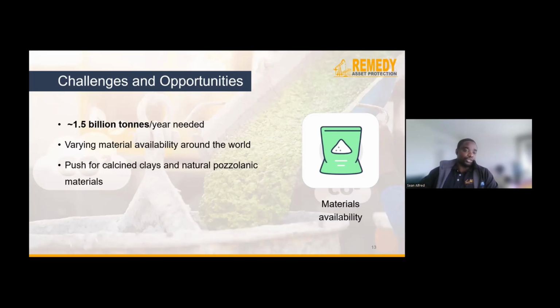And further substitution and replacement depend on locally available materials. For example, in Europe, there's limited availability of fly ash and slag, and there's already a push toward alternative systems incorporating limestone and metakaolin. And here in Australia, we have limestone, slag, and fly ash, which are prevalent SCMs used within industry. And you already know, with fly ash for example, in the near future we're going to expect that coal is going to be phased out. And so the supply of this fly ash, as well as slag from the amount of steel production that's there, these availabilities might change over time.